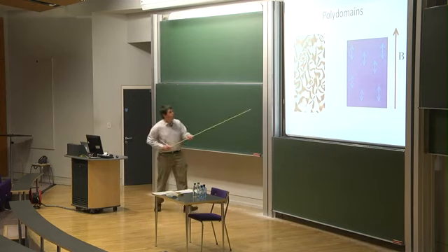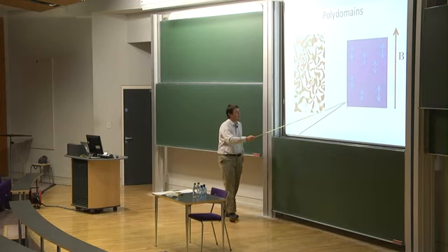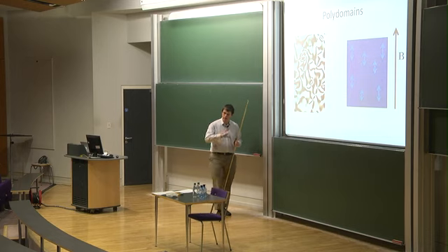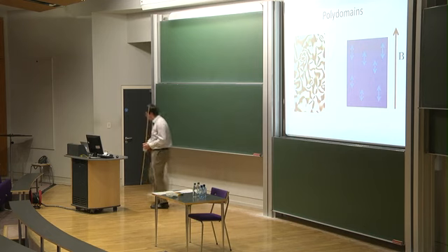So then polydomains, how would we have made a monodomain? We would have made a monodomain by imprinting some direction on the material. Now, we've agreed that you can't really do that just by cross-linking in the nematic state, but you could apply a big magnetic field or a big stress field or some such during the cross-linking process to weakly make one direction globally a slightly preferred direction. And then all the domains would know that, although they were basically soft and most directions had nearly the same energy, there is one direction which is slightly preferred, and they all agree globally on this energy because we imprinted it at cross-linking.